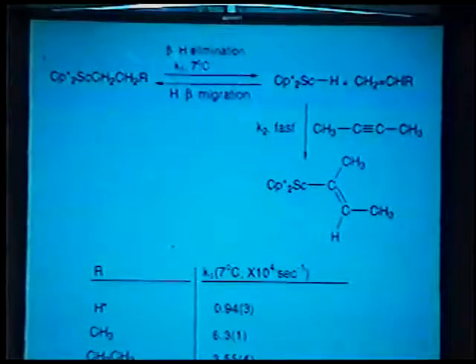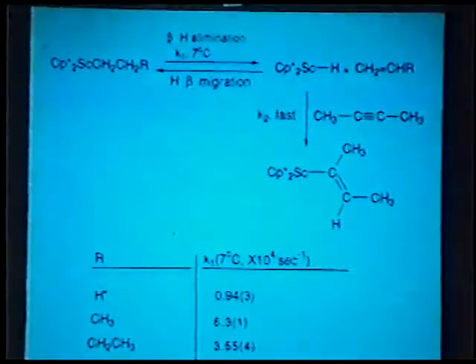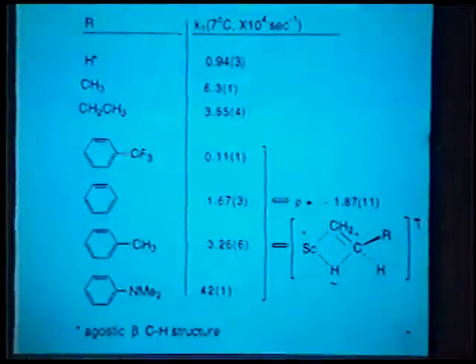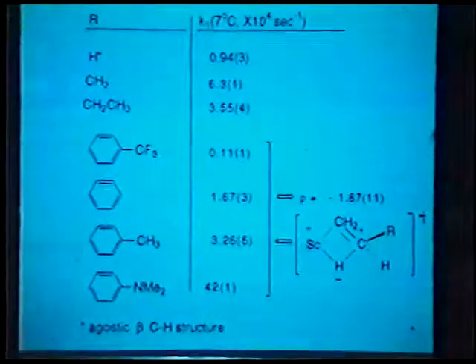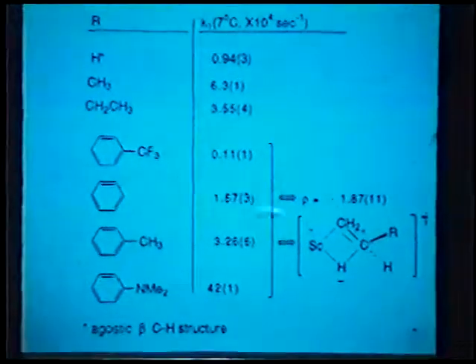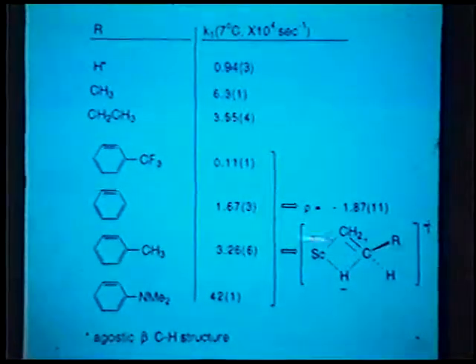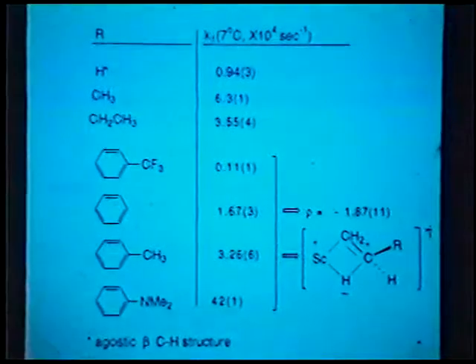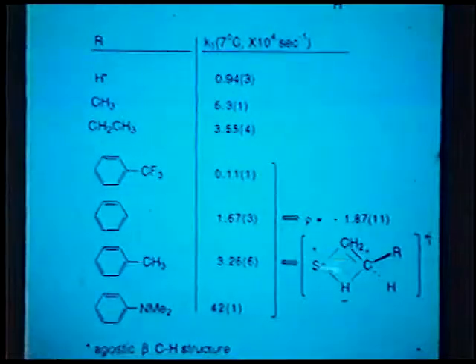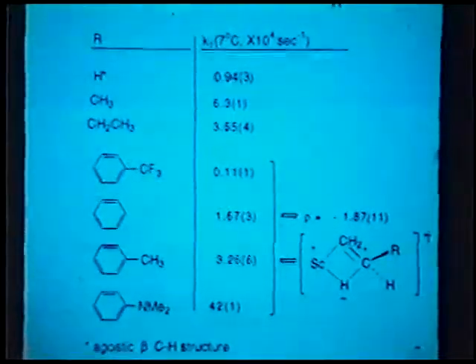And we've examined the effects of beta substituents on the rate of beta hydrogen elimination. I think the clearest picture is here in the alkyl series, where you can see electron releasing groups accelerate, electron withdrawing groups decelerate the rate of beta hydrogen elimination. Not surprising, I hope, given what I told you about the scandium center. It implies the polarity in the transition state is very much like that shown here, with this electrophilic scandium center ripping a hydride off the beta carbon, implying substantial positive charge buildup on the beta carbon. Sort of carbonium ion-like transition states seem to be prevalent in these early, low electron count type systems.